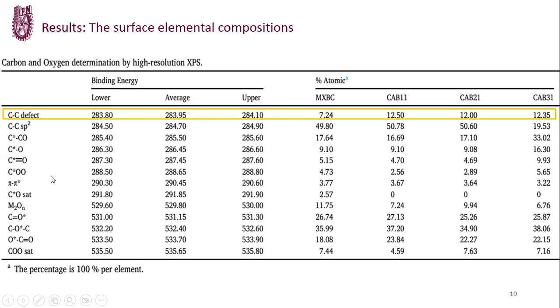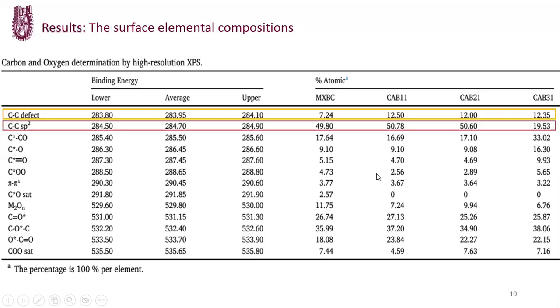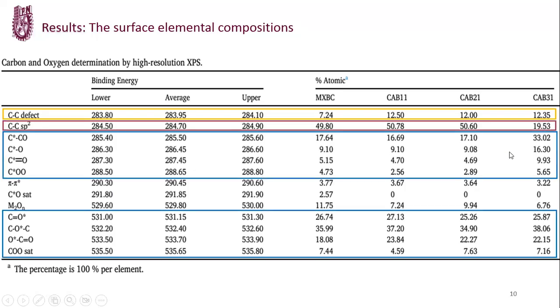We can see that the carbon-carbon defects grow, in a general trend, with the amount of potassium hydroxide used. The carbon-carbon bond is the most abundant species in all the materials, except for the most oxidized one. And the oxygenated groups population of the materials increases proportionally with the amount of potassium hydroxide used in thermal treatment. It is worth noticing that the activated carbon 31 material exceeds almost twice the amount of oxygenated functional groups relative to the two first samples.